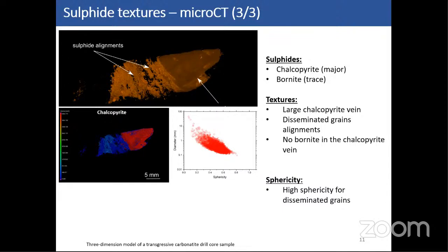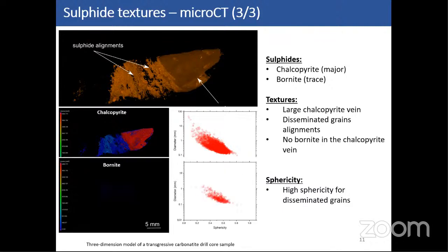So what the mineral liberation analysis showed is that there is a presence of very small fractures and veinlets, which allow the circulation of potential fluids, triggering the precipitation of the sulfides. So what it's possible to deduce from this map is that the fractures and the veinlets are smaller than the resolution of the microCT, so smaller than about 20 to 30 micrometers. Yeah, so again, the domination of chalcopyrite over bornite.